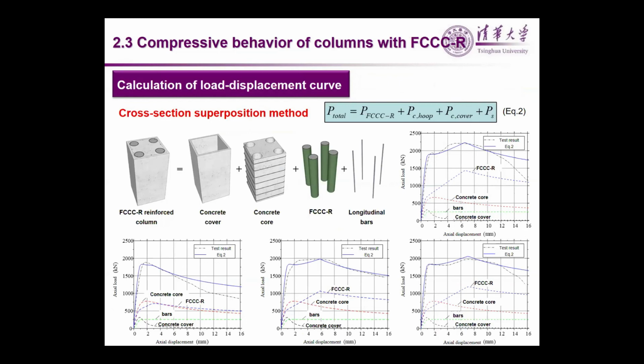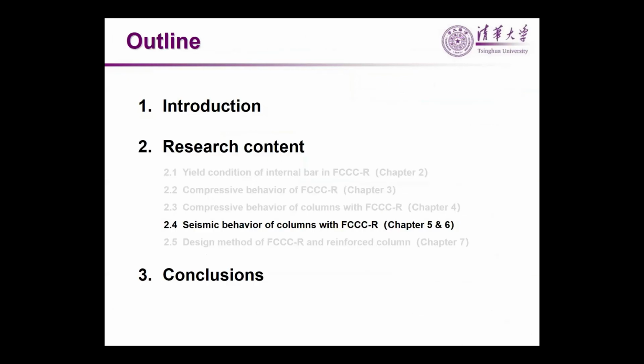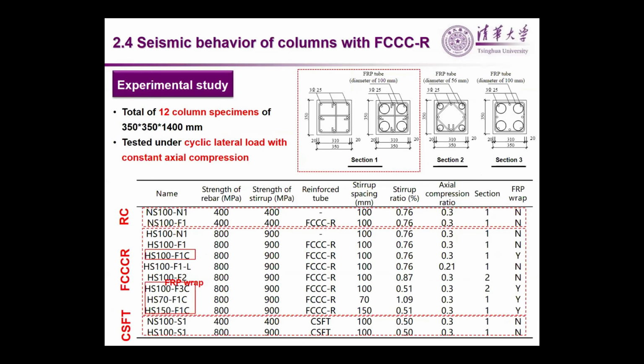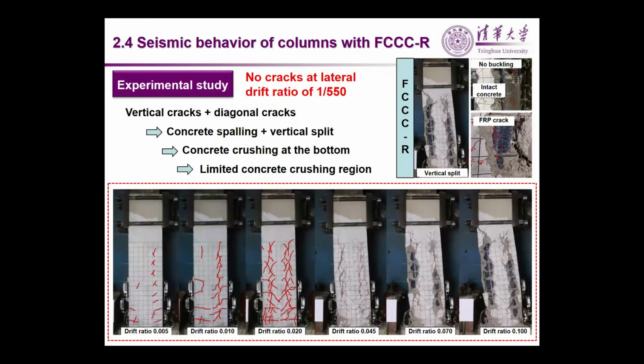Well, in chapters 5 and 6, seismic performance of the FCCC-R reinforced columns is studied experimentally and numerically. The experimental study was firstly carried out under the combination of constant axial load and cyclic lateral load. During the test for columns with FCCC-R, no local buckling of the vertical rebar or severe concrete crushing is observed at the plastic hinge zone. All the composite columns illustrate a vertical splitting failure pattern, which indicated that the bond between the FRP tube and the outside concrete cover has a great influence on the utilization of the FCCC-R.